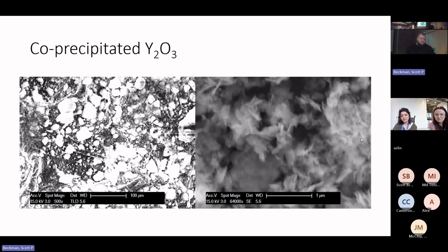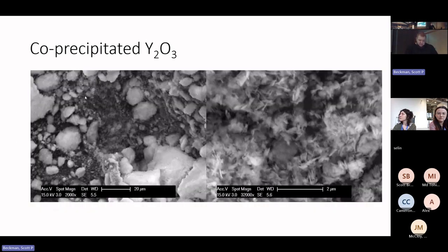And they also were very, very prone to forming these large agglomerates that you can see here, which initially we thought were a problem, but we've since discovered that perhaps some degree of agglomeration is actually ideal, and I'll get into that later when we discuss the outcomes of some of our experimentations.